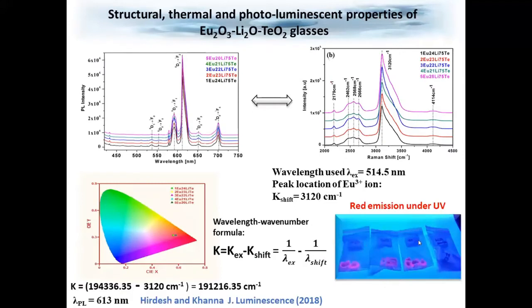And you can see these europium lithium tellurite samples. They are placed in some poly bags, and we expose these poly bags to near UV light of wavelength 350 nanometers. And what you see is this strong red color, very strong red light, when you expose it to near UV light. And these are again the photoluminescence peaks. From the Raman studies also, you can do photoluminescence spectroscopic studies within a certain limited wavelength range.